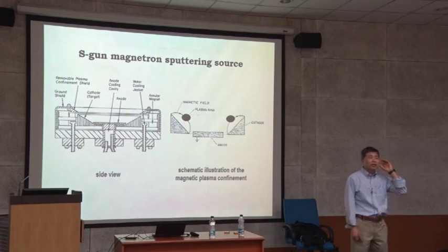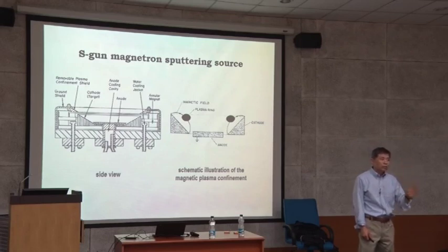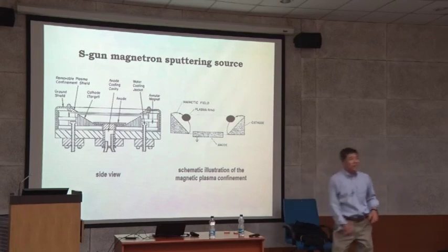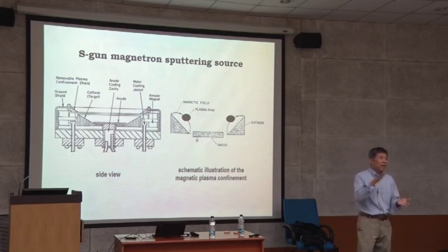Okay, a good question. For a ferromagnetic target, like iron and cobalt, or those kinds of metals, the sputtering is harder. So for magnetic material, your target thickness has to be very thin. Normally, the standard target thickness is 1/8 inch thick, which is 0.125 inch. Usually magnetic material is half of that thickness, 1/16 inch thick, which is very thin.